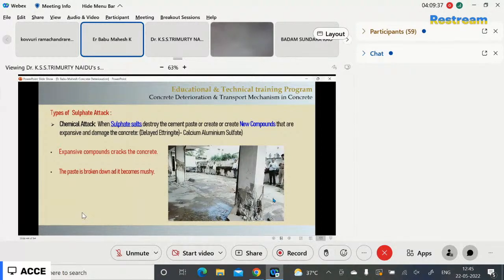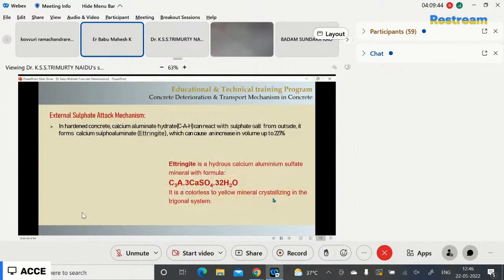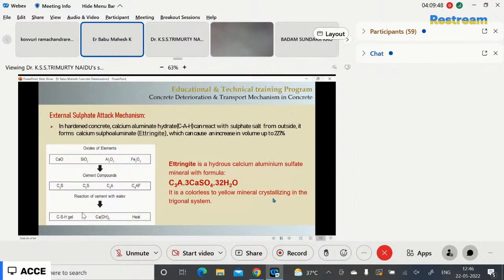In such conditions, the paste is broken down and becomes mushy. Such conditions nowadays lead to distress and collapse of columns. In hardened concrete, calcium aluminate hydrate can react with sulfate from outside. It forms calcium sulfoaluminate, which can cause an increase in volume of up to 227%. That is very expansive. So we are using low C3A content cements, SRC cements, where sulfates are rich in the soil. Next.